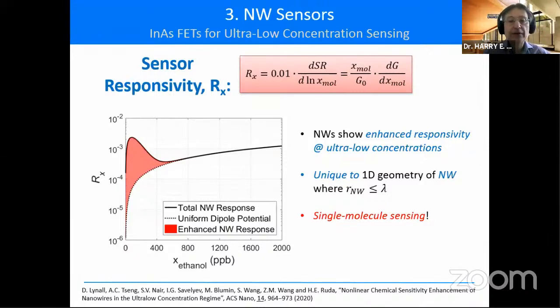And the way we do it is if you look at the derivative of the sensor response with respect to exposure, what you see is that in the uniform dipole approximation, the curve just goes down monotonously, as shown by the little dashed line, down, which means that there's no improvement when we go to low concentrations. So where's the improvement coming from?